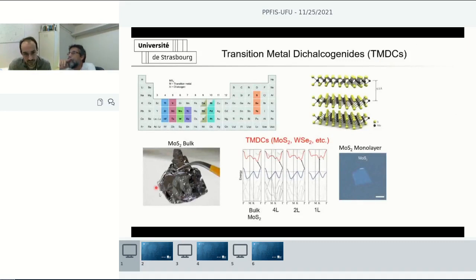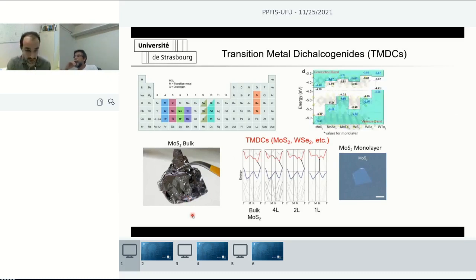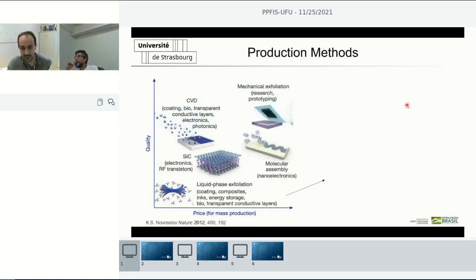These are interesting semiconductor materials. Here's a picture of a molybdenum disulfide crystal. And this material, in its bulk form, is a semiconductor with an indirect band gap. But when you go down to monolayer, it's a direct band gap semiconductor. So this kind of material became very interesting for optoelectronics. And this class of materials can present different band gap energies: molybdenum disulfide, molybdenum diselenide, molybdenum telluride. So they are very appealing for optoelectronics, electronics in general.